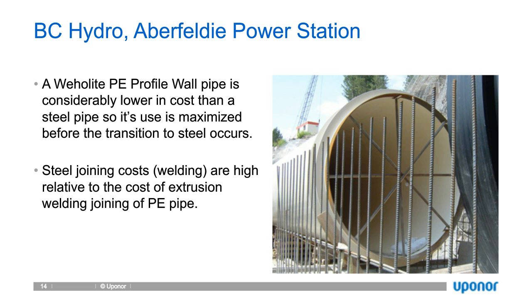So Weholite polyethylene profile wall pipe is considerably lower in cost than a steel pipe. So designers typically want to maximize its use before the transition to steel occurs. And it's possible to do that, to accumulate as much head as you can by running the pipe at a fairly flat elevation. And that's really because of the limitations in pressure that are available with polyethylene pipe.